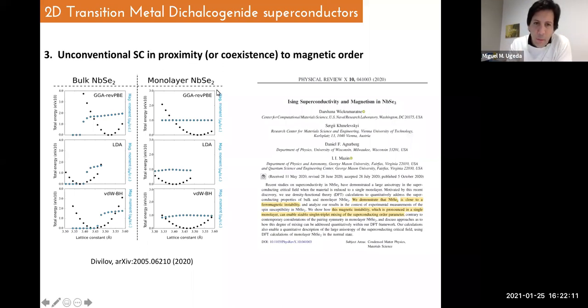For example, this is a fully DFT work in which we are somehow involved by our colleague, Felix Indurain. So he has studied the electronic structure of niobium diselenide for bulk and for the monolayer limit. And it turns out that no matter the pseudopotential he uses, the most stable solution has a magnetic moment. So the ground state of niobium diselenide in the monolayer limit in principle is ferromagnetic, as you can see here, with a magnetic moment of around one Bohr magneton per unit cell.